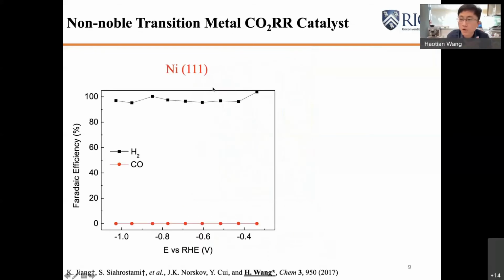nickel, cobalt, and so on, at the very beginning, dating back to 5 years ago, people really picked up those nickel, cobalt, iron, low-cost transition metals as good candidates for CO2 reduction, mainly because of two reasons. Number one is they are generally very good HER catalysts, so they generate hydrogen very actively. So you don't want to start with materials that have a lot of competition on the HER side.